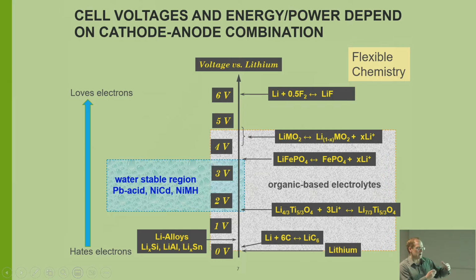So how can you get higher voltage batteries? Remember, higher voltage gives you higher power, and it gives you higher energy. Water is really limiting us to basically a 1.5, almost 2 volt window, like for lead acid. If we can get outside of water, we can look at other cell couples, things like lithium and graphite. Graphite is just about 100 millivolts above lithium in terms of potential when it's fully lithiated. And on the positive side, we can look at these layered lithium metal oxide materials. You'll notice these are up around 4.5 volts. The graphite is around 100 millivolts.